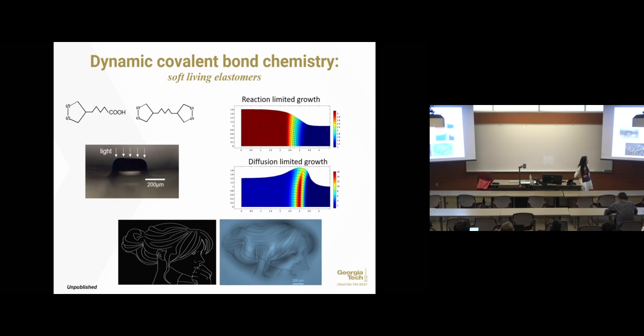Now we can do it in high resolution. This is just a random picture we downloaded from online, used as a photo mask. And then you shine light on it, and it generated this 3D-like picture on the surface. And this scale bar you can see is 200 micron. We can do it in very high resolution.